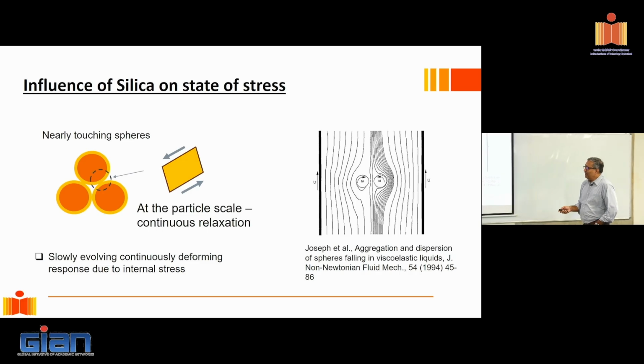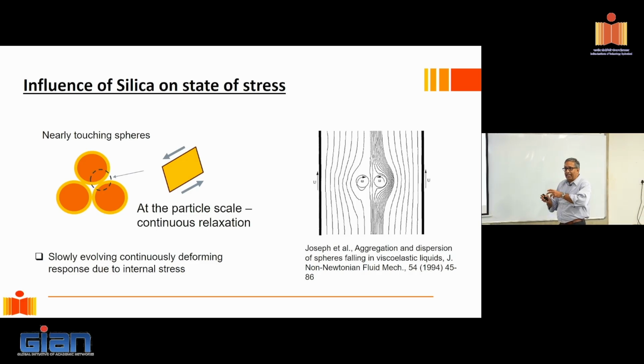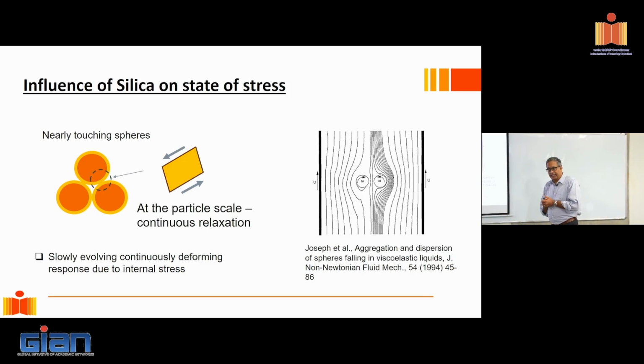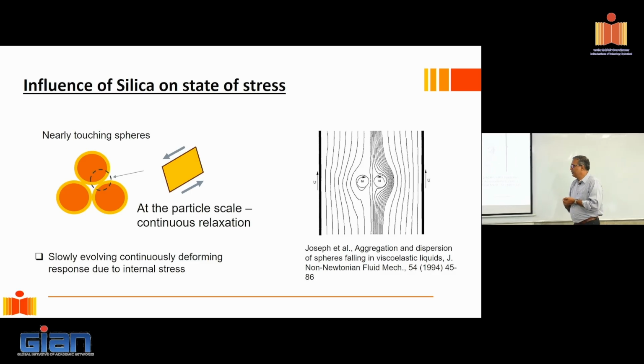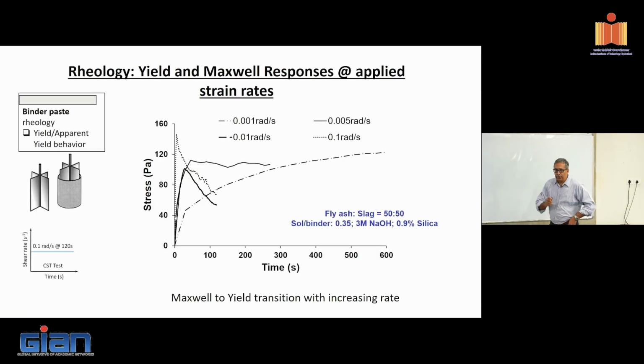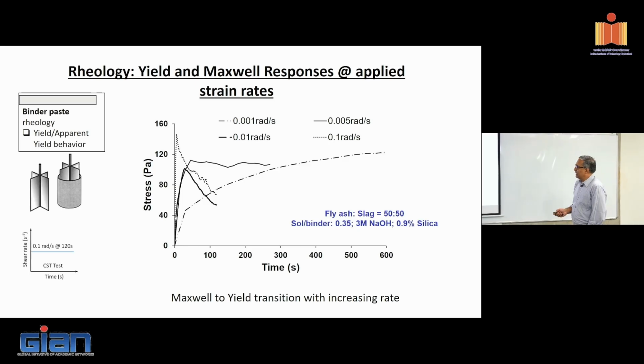And when we have these particles, which are, let's say, fly ash, coated with the solution of sodium hydroxide and sodium silicate, basically the same shearing type action takes place whenever these particles even are to come to rest. What would happen now? This fluid which is in this gap here is going to continuously deform. We just saw that. So what will happen? It will basically continue to deform and lose its shape. It will continue to flow. And this is one of the first problems we encountered when we were looking at alkali activated materials. Let me show you what the rheological behavior of this alkali activated material looks like.